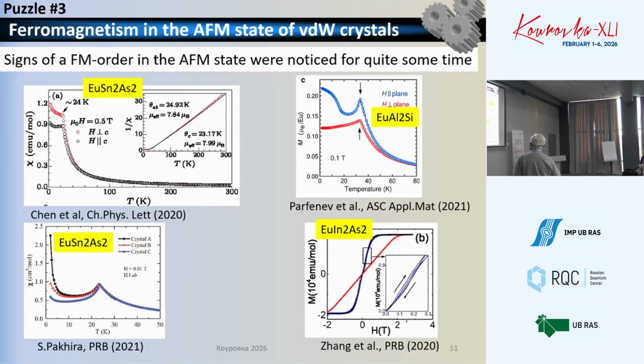And this is, of course, not the behavior typical for an antiferromagnet. It points at some signatures of ferromagnetism. What experimentalists often do, they apply a magnetic field, maybe below 1 Tesla, maybe 0.2 Tesla, and then it is washed out, and it seems to be a nice picture which may be published. But in fact, the question exists. Some people refer to residual magnetic impurities as maybe responsible for this ferromagnetic type behavior in susceptibility. In some samples, during measurements, you can notice a weak hysteresis.